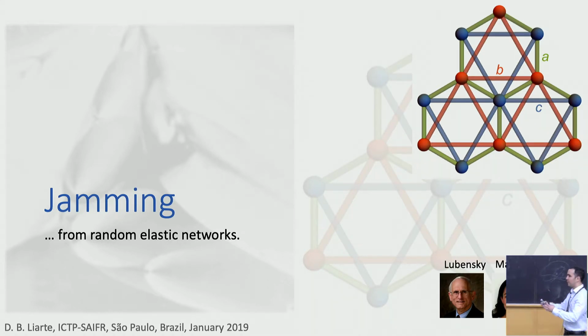we are applying this theory of Martensites. I gave 3 ingredients. You start with variants. So you describe each region, for instance, by one variant. But you can also apply a general symmetry transformation to this region that doesn't change the energy. And that's where the symmetry group enters. For the Martensite case, you just rotate the variants and combine the different variants by rotating them. For the Smectic case, you have this richer group of symmetry. You can apply a Lorentz-Poincare transformation and combine these different regions with different Lorentz-Poincare transformations together.